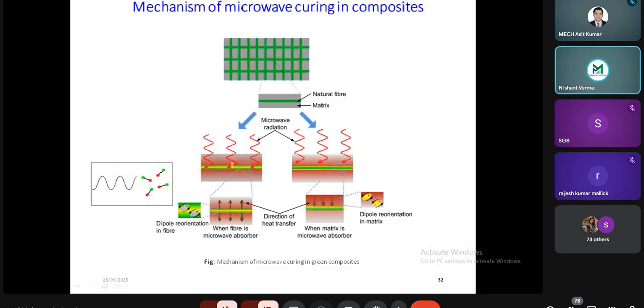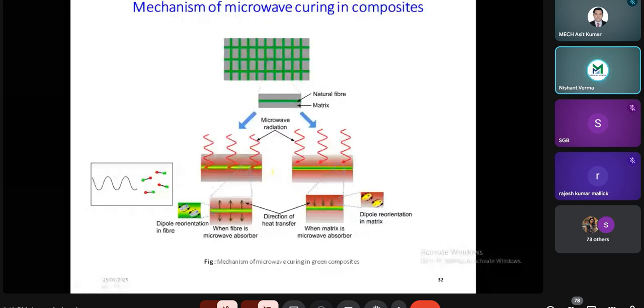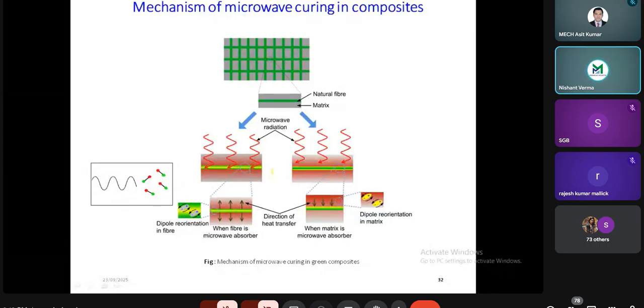In the first case, the reinforcement may be the microwave absorbing material, and the polymer is a microwave transparent material. In the other case, the reinforcement might be the microwave transparent material, and the polymer may be the microwave absorbing material. Whichever the case, if the dielectric constant of the fiber is higher, the microwave will interact with the fiber at a higher rate compared to the matrix material.